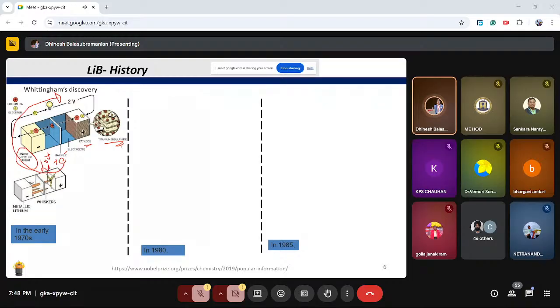And even at that point of time, in 1970, the researchers were facing the issue of battery fire. This talks about the battery fire in the initial stage, where a whisker formation forms from the anode to the cathode side. The whisker is a solid layer produced because of this electrochemical reaction, and it forms a connection between the anode and cathode side, resulting in short circuiting. As an end result, the battery fire issue was initiated. So battery fire is not a new issue that the entire research community is facing only now in 2020 or later. It is an issue that researchers have been fighting for the past 40 to 50 years, from the earlier research progress of lithium-ion battery working.